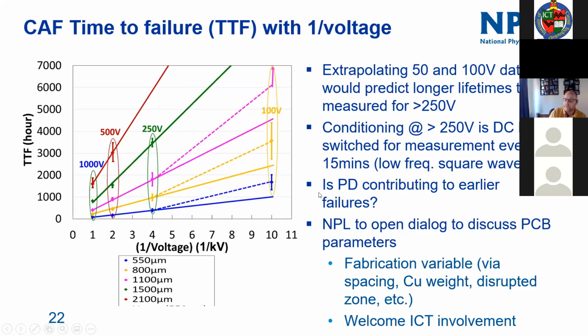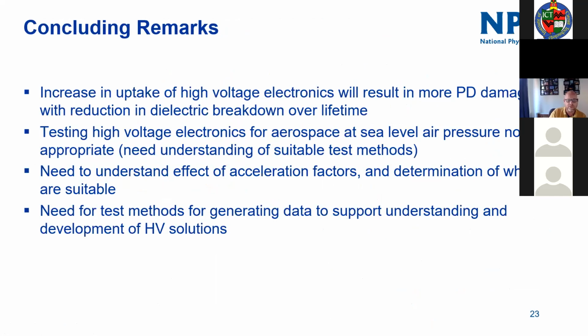What we're not sure about at the moment, and this is pure hypothesis on my part, is whether there's any PD occurring potentially at these higher voltages, which is causing these premature failures of the higher voltage system. So, again, if we can open a dialogue with people looking at fabrication variables, via spacings, copper weights, disrupted zones, etc., then we'd obviously welcome that involvement.